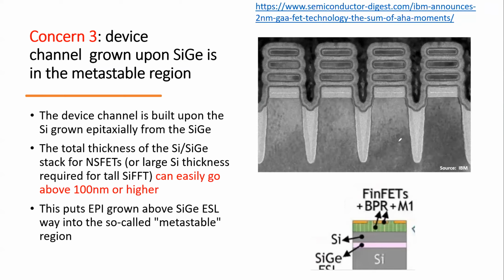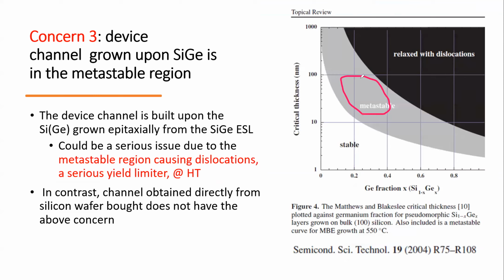How thick do you need to grow? Say, in here, the whole stack, all the way here, including this STI, this could run you close to 100 nanometers, sometimes even higher, right? So this thickness is very thick. And then how thick can you grow before it becomes a problem? What I meant is why it's called a metastable region. A metastable region is the epitaxial growth where, if you hit the black line here, it will relax with dislocation. For example, if you have 40% germanium and then you grow 100 nanometers,